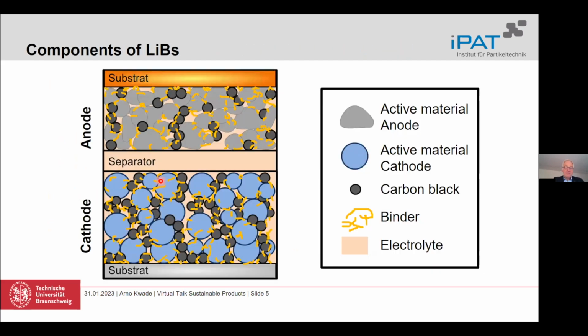Coming back to the lithium-ion batteries, maybe most of you, but maybe not all, know that these batteries are composed of particles. So on the anode side, we have graphite particles or graphite and silicon particles today. And on the cathode side, these are lithium metal oxides or lithium metal phosphates. And in these particles, we store the energy by transporting ions via the separator, via the electrolyte from the cathode to the anode if we charge the battery, and then during discharging from the anode back to the cathode.